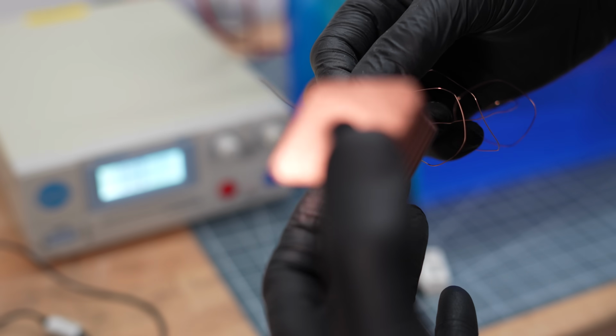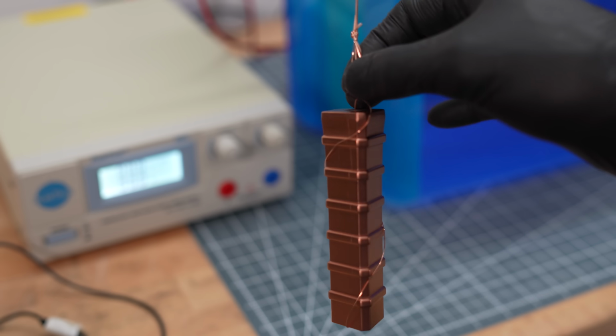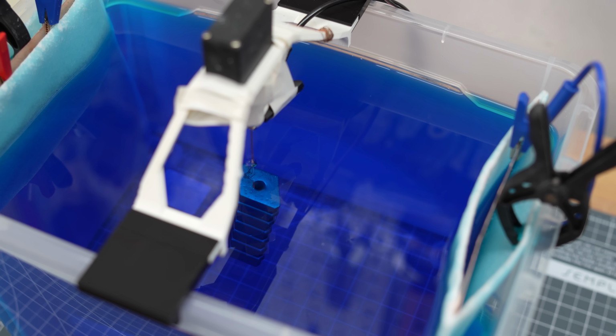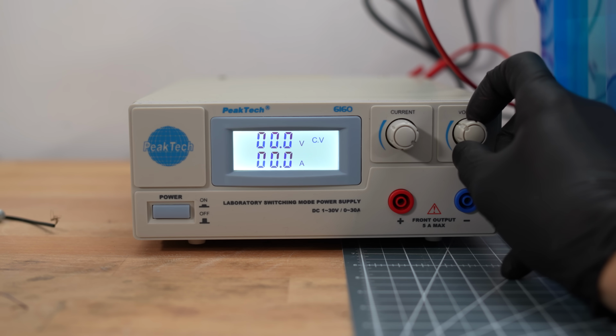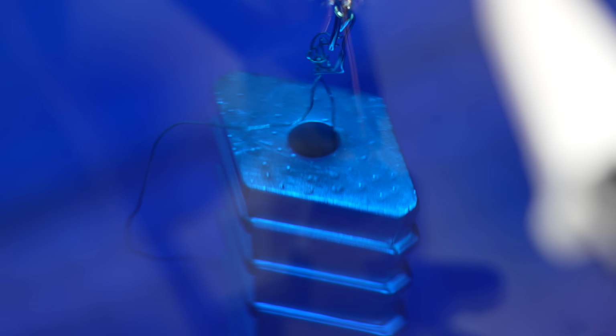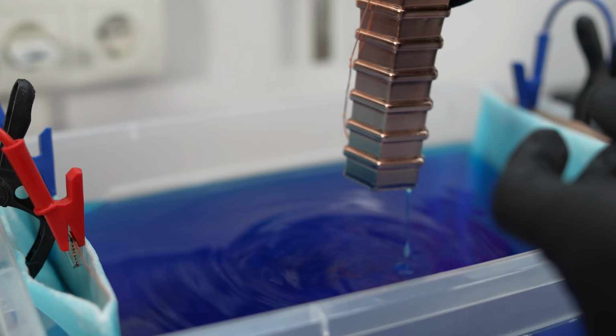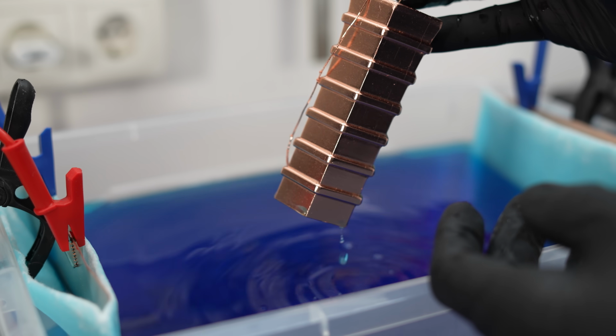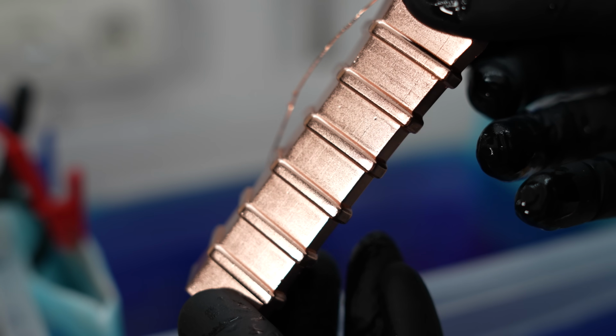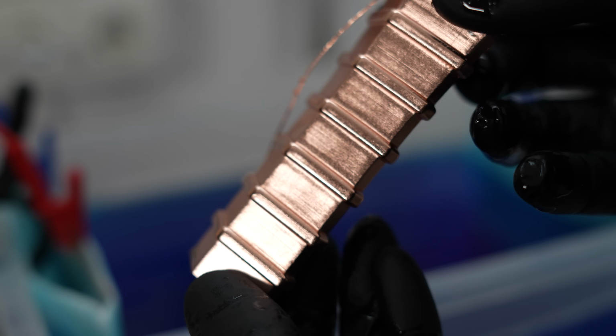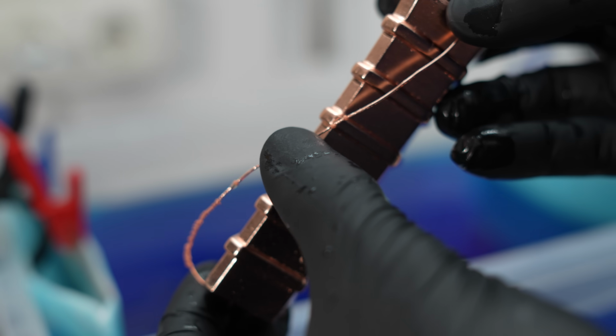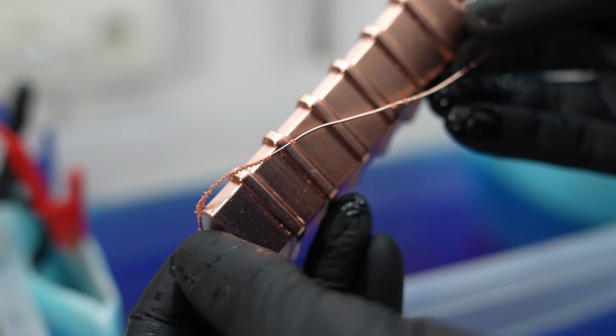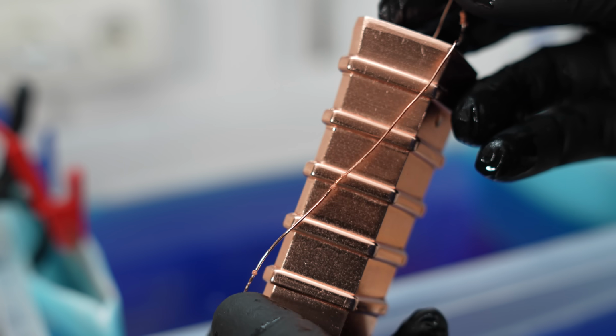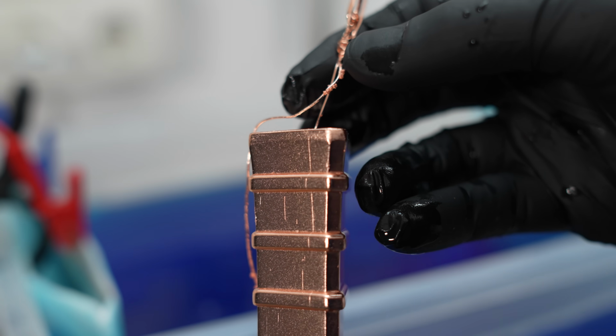Wrap the piece with copper wire and optionally hang it on a rotary jig. Then set the current to 0.2 volts and electroform the whole thing for 4 hours while you slowly increase to 1 volt. Uh-oh, rough surface, probably from too little contact area of the wires and too fast, impatient plating. Happens from time to time. Fortunately, it can be saved and it will be covered by leather later. I should be more careful next time.